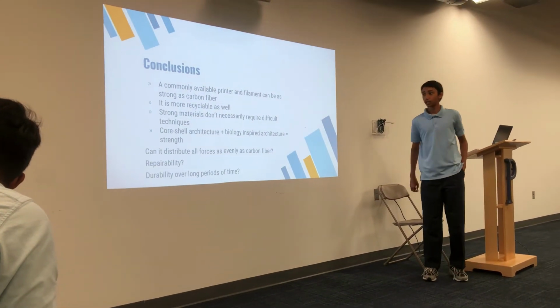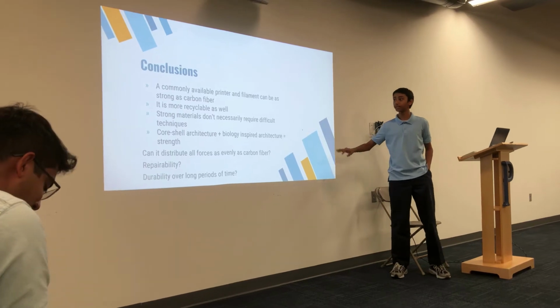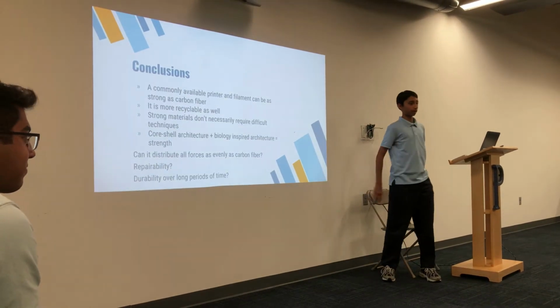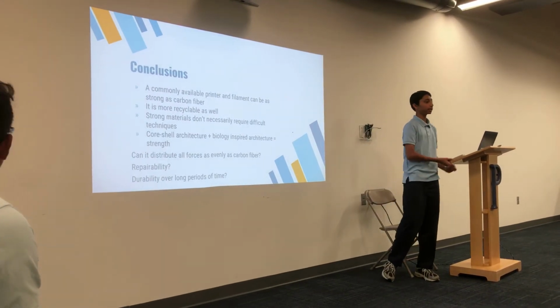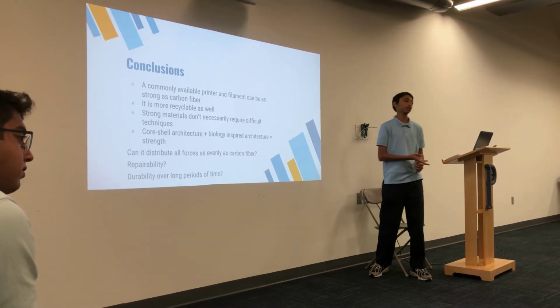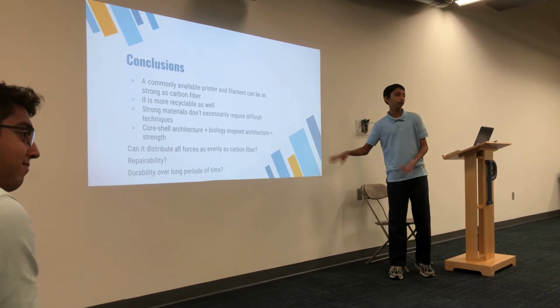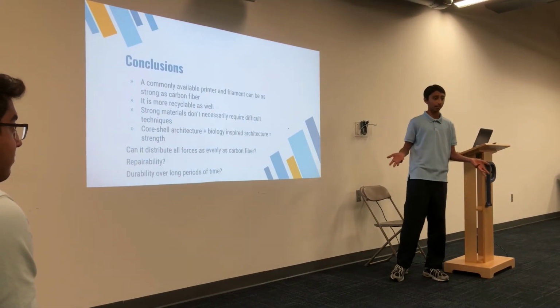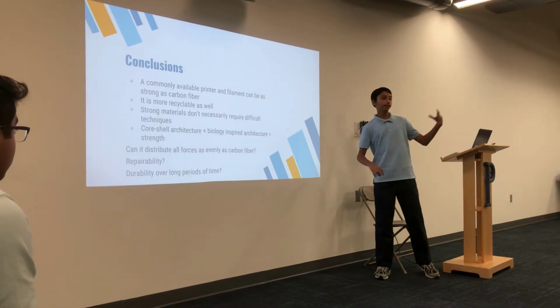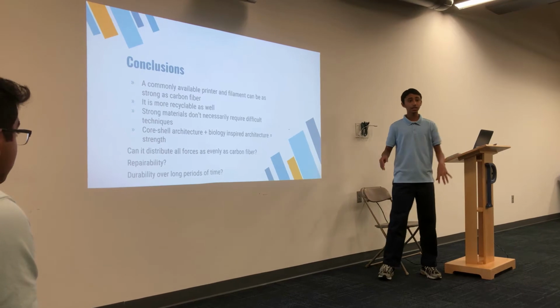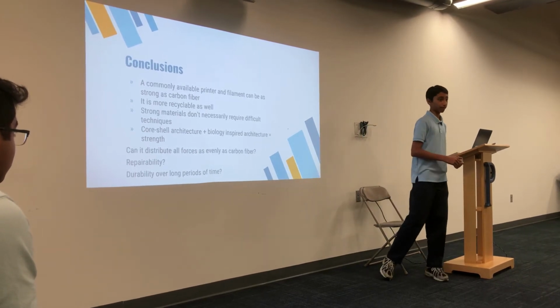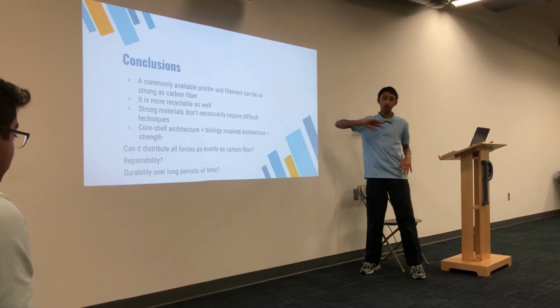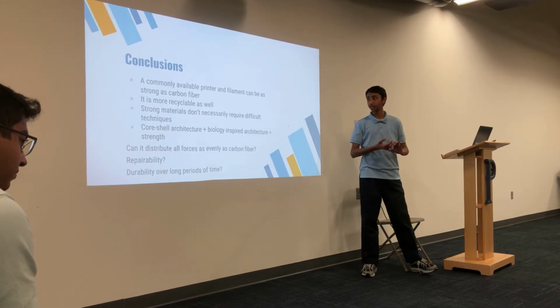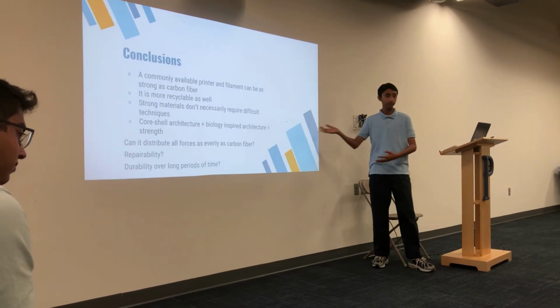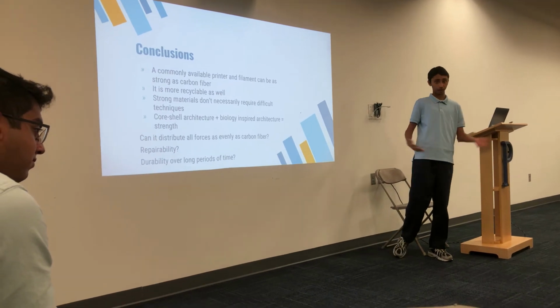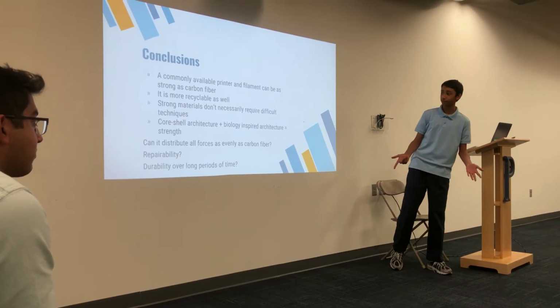So the conclusions. Basically what this means is that a commonly available printer, this $2,000 printer, and this commonly available off-the-shelf filament can be as strong as carbon fiber. And there's a figure which I chose not to include because it's very complicated, but it does show that the amount of strain that this material can take is very similar to that of carbon fiber. So it's as strong as carbon fiber, and it's certainly more recyclable. At least you can recycle this using a hydrolysis reaction. What are you going to do with broken carbon fiber?